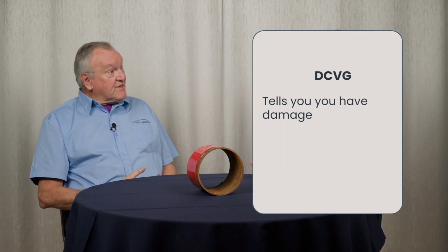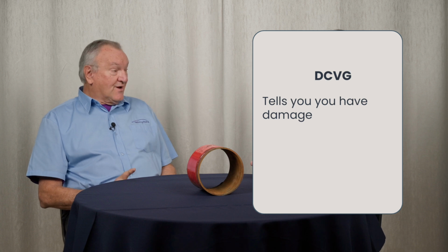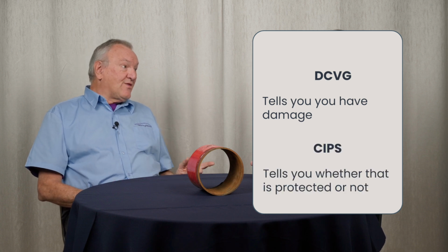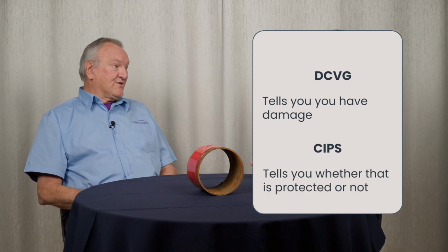So the DCVG tells you you've got a damage, and the CIPS tells you whether that is protected or not. And the two are completely different. So you can have coating defects, but still have an operational cathodic protection system, which means that your pipeline is not corroding. So it's not a high-risk situation. Right. So this combined survey kills two birds with one stone.